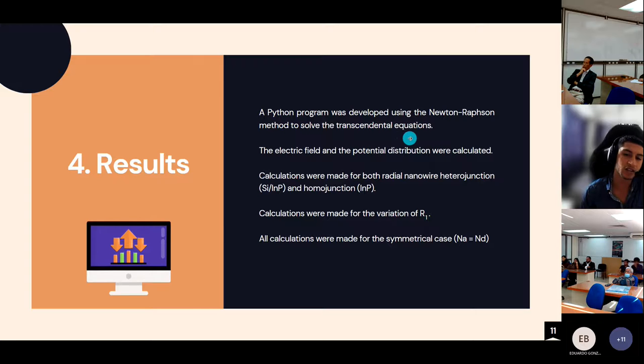The electric field and the potential distribution were calculated. The calculations were made for both the radial nanowire heterojunction, silicon indium phosphide, and the indium phosphide homojunction. The calculations were made for the variation of R1, and all calculations were made for the symmetric case, where acceptor density is equal to donor density.